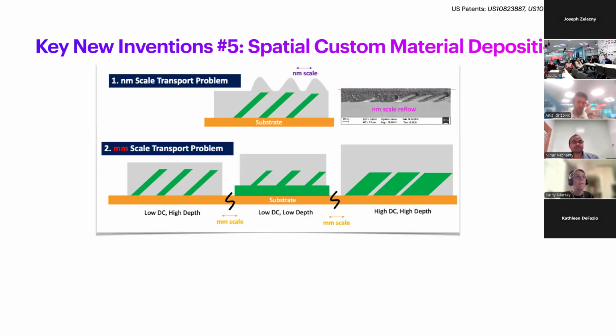The final key invention was that with the overcoats. Typical high-efficiency grating designs demand overcoats that have no ripples over gratings and over the whole waveguide area, so having a constant thickness over all the gratings, irrespective of their fill factor or their depth. You can break this into two sub-problems. The first is eliminating the ripples over the gratings, which is a nanometer-scale reflow requirement for this overcoat material.